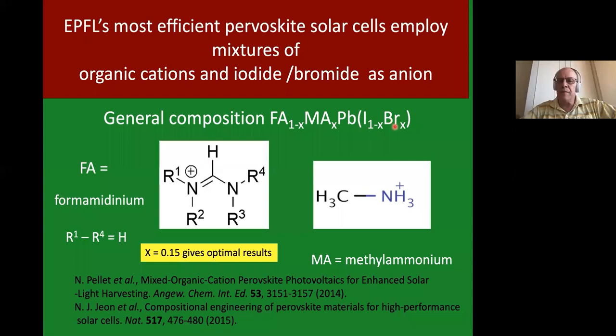So it increases the band gap, which is something we don't want, if we want to use it in a tandem cell. Also the cation can be changed. Methyl ammonium was the first one to use, but then people here in Grätzel's lab, 2014 is this published, started to use the formamidinium. We call this the double cation recipe with the double halide. And that was for some time taking perovskite to about 20% in efficiency.